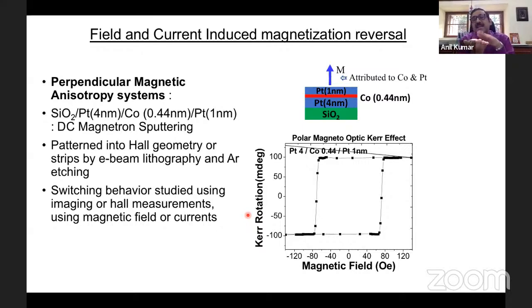But if this material is ferromagnetic, then the reflected beam will have a slight change in its plane of polarization with respect to the incident beam, and the rotation is called the Kerr rotation. That Kerr rotation is proportional to the magnetization. Now, if I measure the Kerr rotation as a function of applied magnetic field, I will get the magnetization versus applied magnetic field curve.